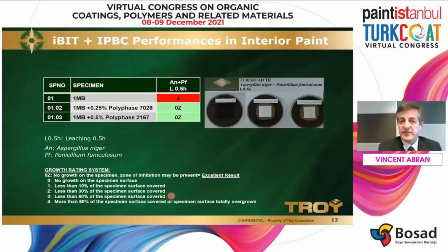If we look at the fungi test, here we have an agar diffusion test concept. We see that the same paint without antimicrobial protection has fungi growing onto the specimen. So the specimen is completely grown. Of course, if we start to apply the antimicrobial product at 0.5%, we have a zone of inhibition around the specimen, and with a minimum leaching in water to simulate any cleaning or any leaching from the surface. And we see that it's a very nice result with complete zone of inhibition around the sample. So this is to show you the antibacterial test and the antifungal test for complete antimicrobial protection of the surface.